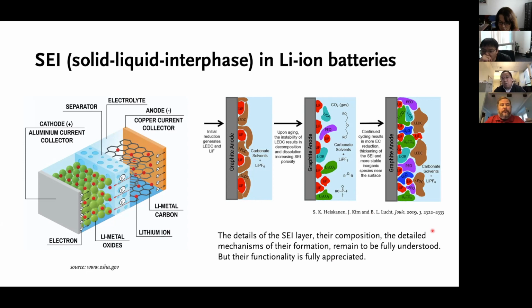As a matter of fact, if you look at the history of battery development, between the 1970s and early 1990s, researchers really struggled to get reliable performance out of this simple concept. As a result, this concept remained a scientific curiosity. It wasn't until graphite was introduced. And this is a God-given gift, where the reaction between graphite and the electrolyte under electrochemical conditions forms this layer. What we do know today is that this layer contains multiple components. Toward the surface of the electrode is a more inorganic component, such as lithium fluoride, lithium carbonate, and some lithium oxide. And when you move out toward the solution, you have more of an organic component.